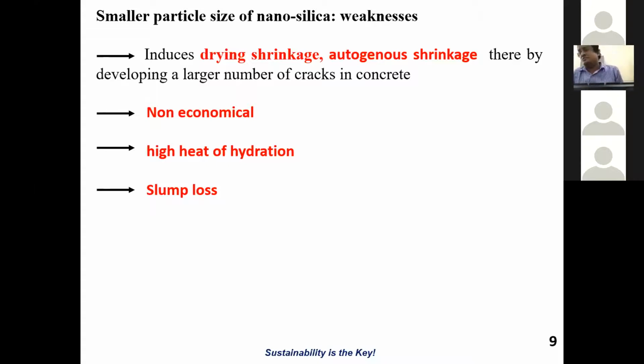Second is that it is non-economical. It is definitely a costly material, I will tell you. Third is high heat of hydration. We have a smaller particle size, so the hydration process is going to be very fast, the reactivity is going to be very fast, so the heat of hydration is going to be very high. Fourth is slump loss. Because of the high heat of hydration and the smaller size of particles, water consumption is going to be more, so you necessarily need a superplasticizer. Without a superplasticizer, you cannot work with nanoparticles. So these are a number of disadvantages because of which construction managers and we civil engineers are unable to bring the usage of nanoparticles to the fields on a larger scale.